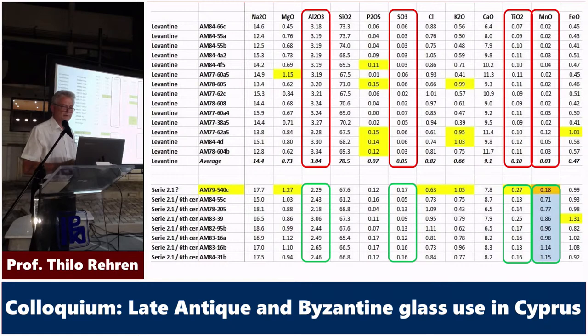Titanium, around 0.1% in the Levantine glass, around 0.15 in the Serie 2.1, and so on. And you see also the quality of data that we need to be sure that 0.13 is actually reliably more than 0.09 weight percent of titanium oxide.